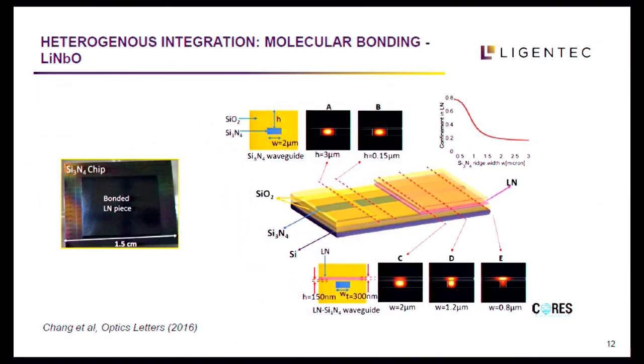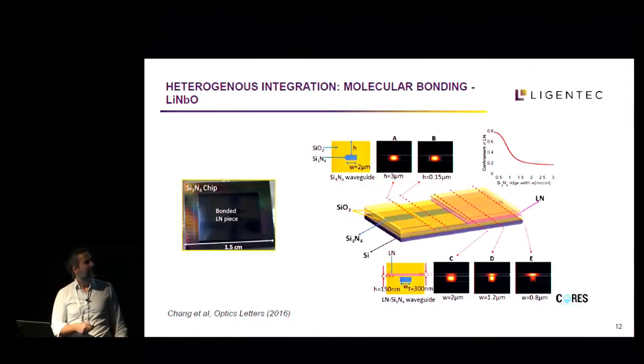Now, if you put all this together, you can make some really interesting devices. So this is a silicon nitride chip with lithium niobate bonded. And you can see that the light comes from one side of the chip to another. And with lithium niobate on silicon, you can make 100G modulators. And you can put as many of these modulators as you like. And again, this is work done with the DARPA program CORES.